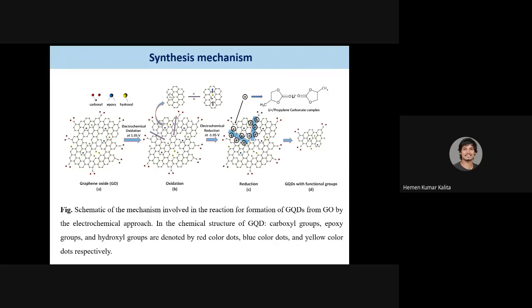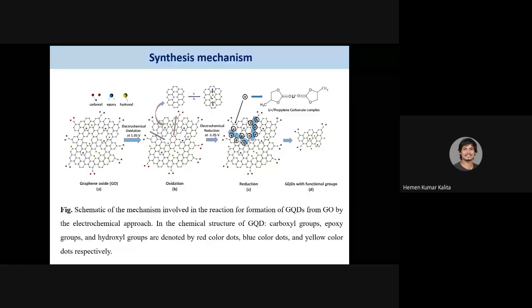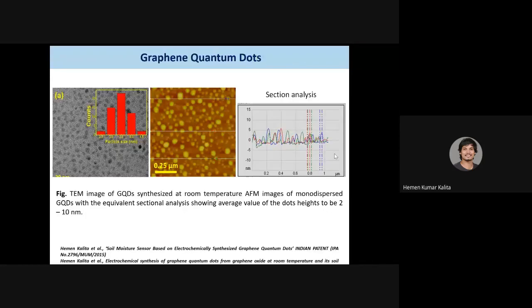In the reduction process, this ion starts to move to the breaking side. After that, when we disperse this, the left out portion, because of this breaking and the intercalation, finally we get a very small piece of graphene oxide, which we termed as a graphene quantum dot. So how does the graphene quantum dot look? This is a TEM image, that is the transmission electron microscopy image of graphene quantum dot. The size in this particular image is around 3 nanometer, 3.5 to be exact.